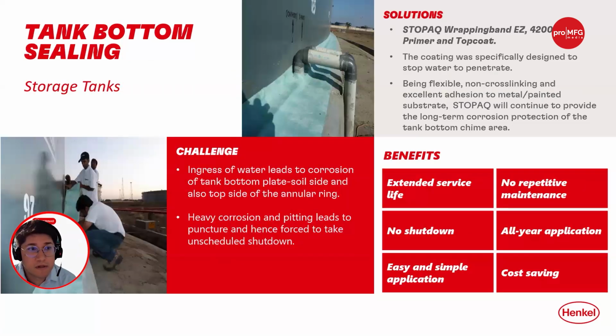Then something very common and that we see more and more often across the regions is the tank base, where you have the concrete base and the metal shell of the tank. Due to the difference in thermal expansion of the materials, we typically see this creates gaps in between, and these gaps then create spaces for moisture and water to ingress, causing a lot of damage to the bottom plates over time. This is extremely complex.